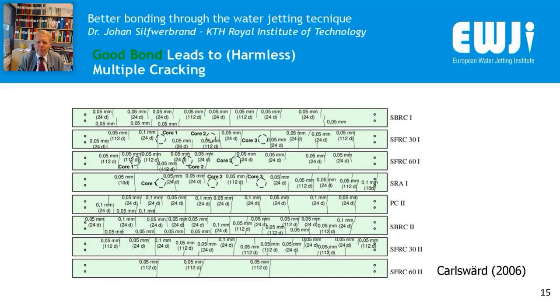This slide is from a colleague of mine, Johan Silfwerbrand in Luleå, in the very north of Sweden. He made his PhD and he was also looking at overlays, and he looked at a case where he had a good bond between the base and the overlay, and you can see here that after some days and weeks, he received some minor cracking due to the differential shrinkage, because the new concrete will shrink and the base is preventing that shrinkage to be free. If you have bond, you will have a lot of small cracks, but all of these are harmless. You can see they are 0.1 and 0.05 millimeters, so they are harmless.